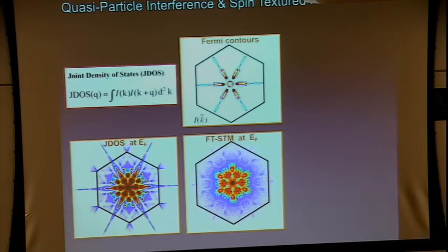Okay. So if you're an electron and you live on this Fermi surface, as we just discussed, if you hit a defect, you can scatter and explore all the different wave vectors that are available, right? So a simple way to make progress is to simply take the ARPES data and autoconvolve it with itself, with a scattering wave vector Q that separates your initial and final state.